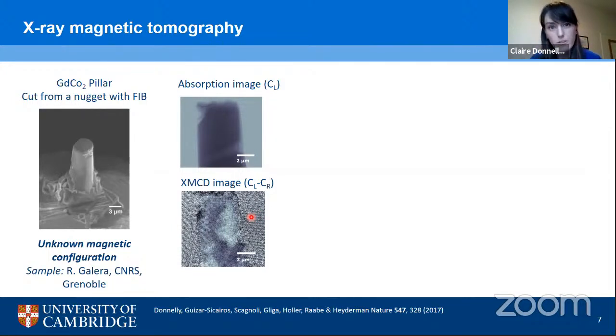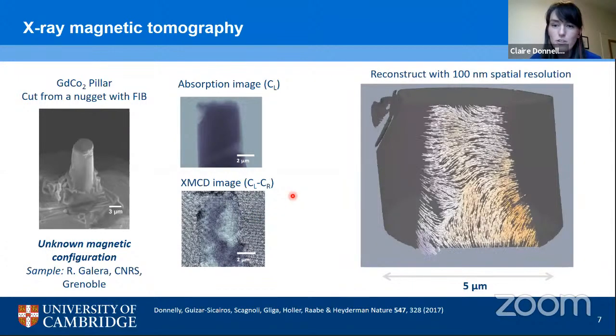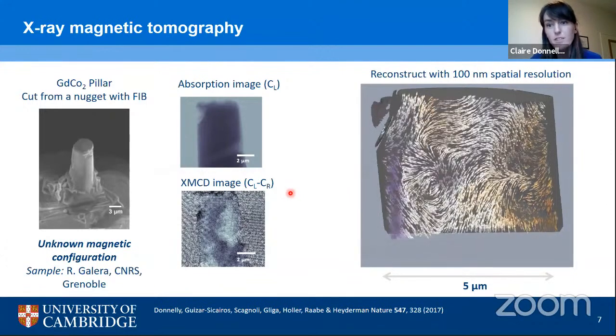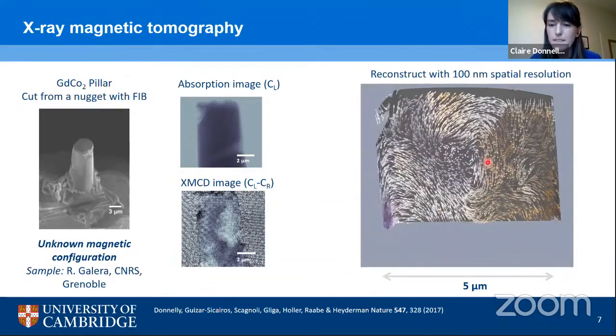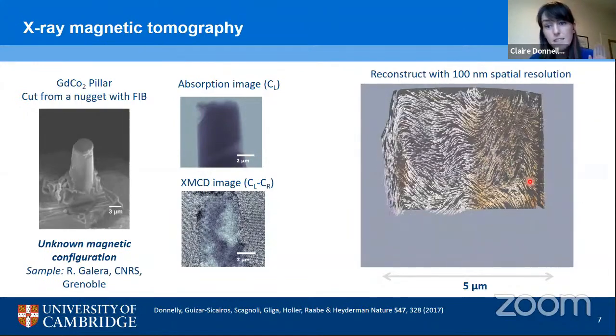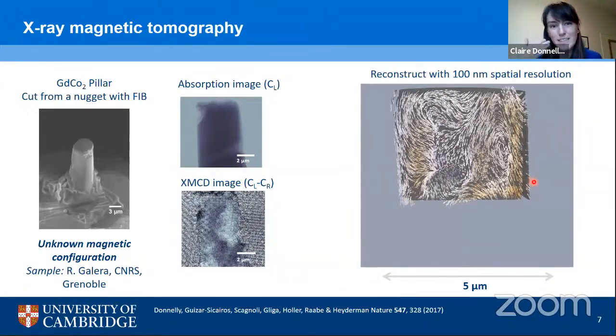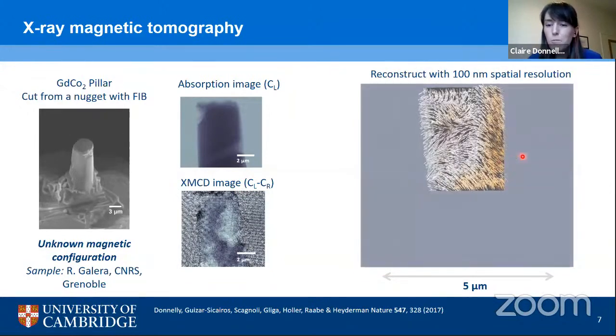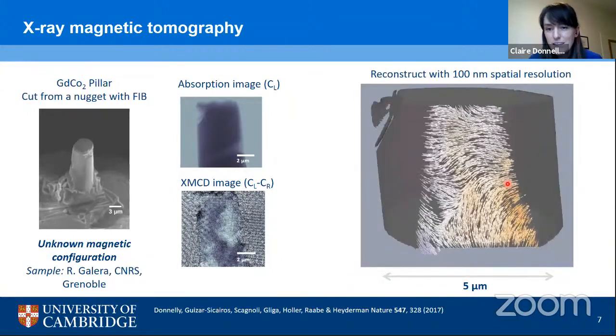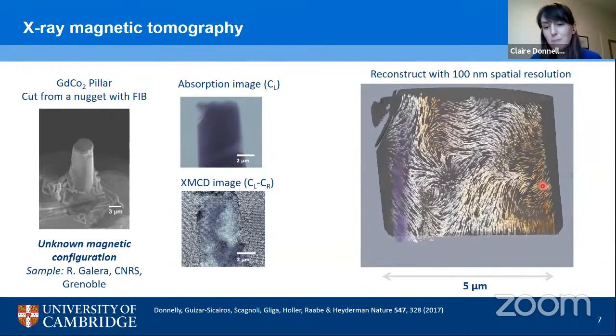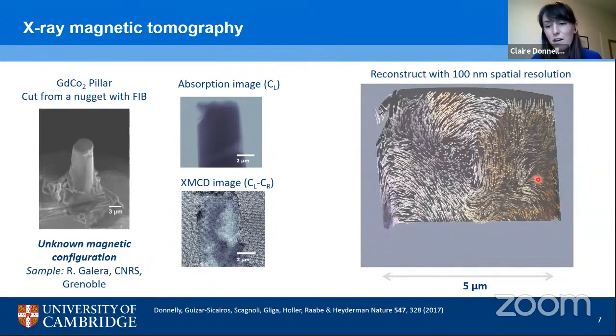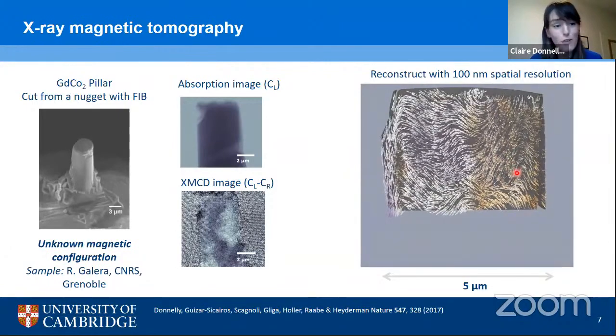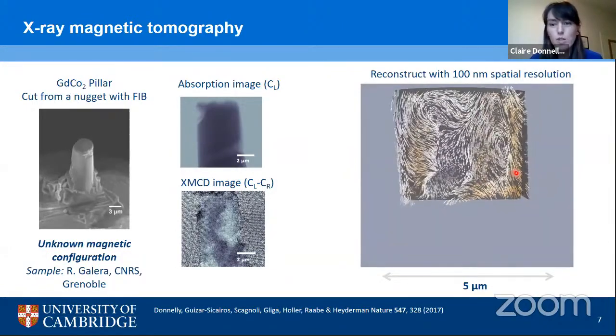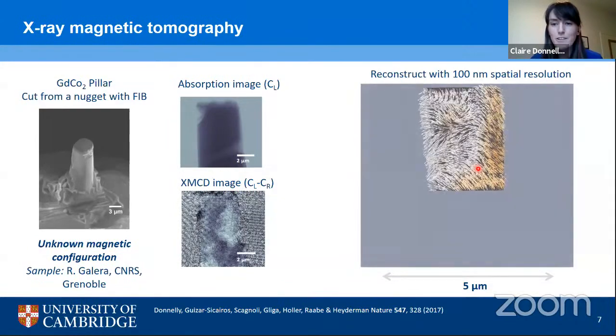So we measure over 1,000 of such projections around many different orientations with respect to the X-rays and use our reconstruction algorithm to reconstruct the internal configuration with 100 nanometers spatial resolution. And you can see this in this video here. I want to emphasize that this is a static configuration. We're just showing it in a relatively dynamic way. But what we can note is that the magnetization appears to be quite smoothly varying. Now this makes sense. It corresponds to what we expect from our knowledge of gadolinium cobalt. But there's also a number of twists and turns in the magnetization, which are quite intriguing.